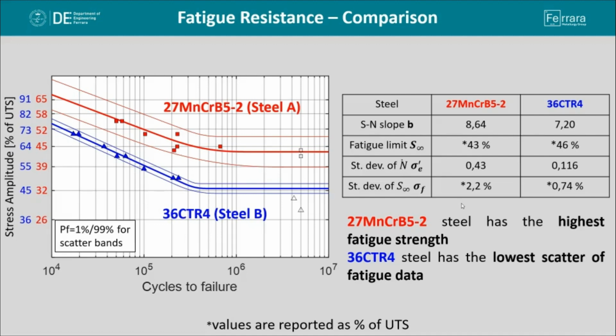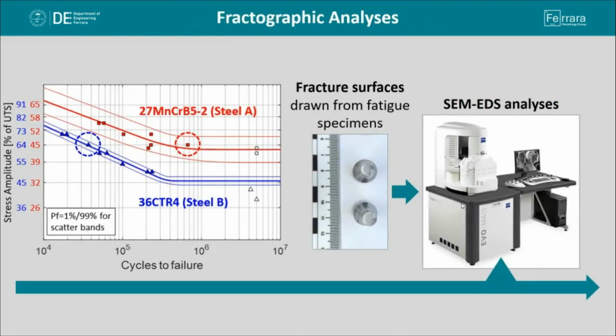These findings are in agreement with the literature studies, which highlighted that increasing tempering temperatures seems to decrease the fatigue resistance of the material because of a softening mechanism occurring within the material itself. Finally, the experimental procedure we adopted also included fractographic analysis carried out on one broken fatigue specimen for each steel, in order to highlight possible differences in terms of fracture behavior by considering two distinct tempering temperatures.